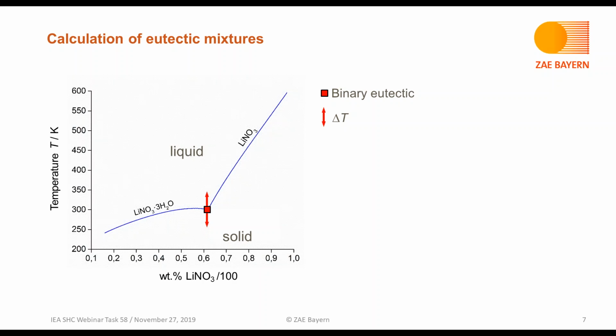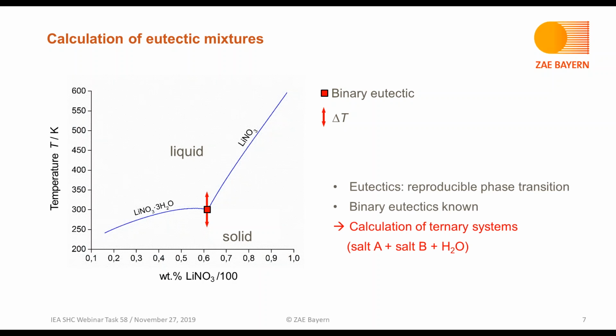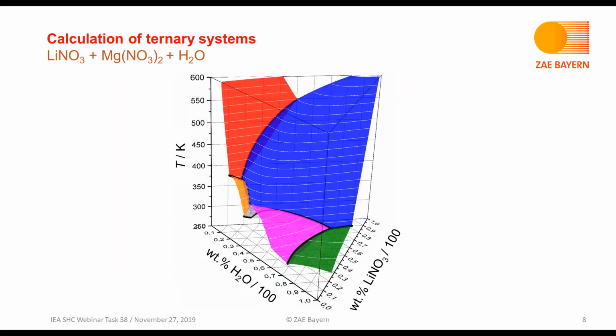If you would, for example, cycle it or use it in the temperature range that is shown here, then we can expect a reproducible transition from solid to liquid and vice versa, and this in a short temperature range. So eutectics, in theory, have a reproducible phase transition, and as binary eutectics, as the example shows, are mostly known, our approach is to calculate ternary systems containing two salts and water.